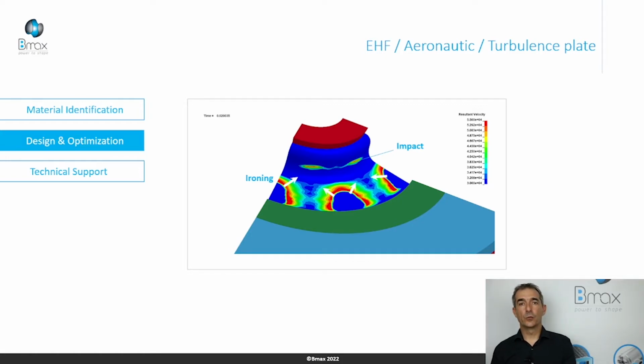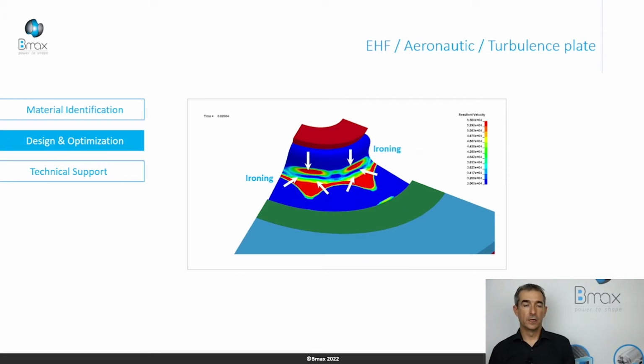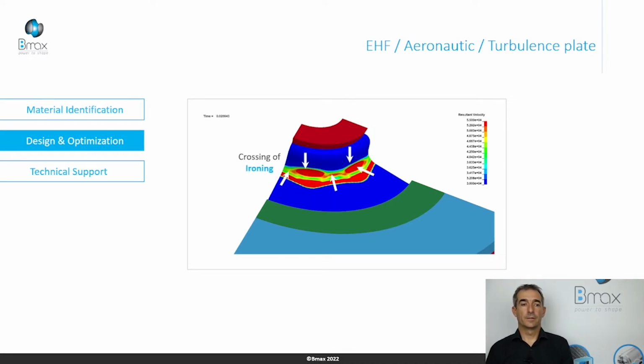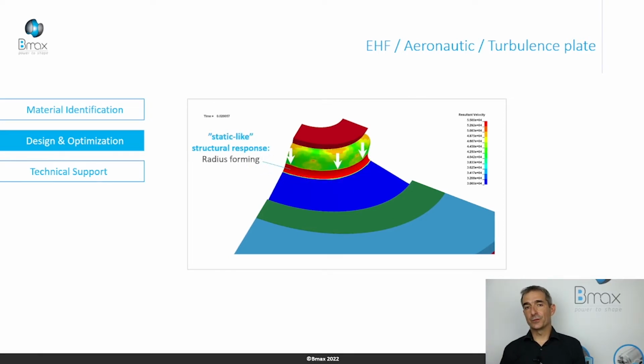At this time, we have an impact on the vertical wall, and this impact creates a second ironing. All the ironing converges to the radius. And we push the material in the radius to have extra material and to limit the thickness reduction on this critical area. At this point, we have a static-like structural response. It's an expansion in the radius. We form the radius, and we create a lot of tensile stress on the vertical wall, and we have a small drawing at this time.